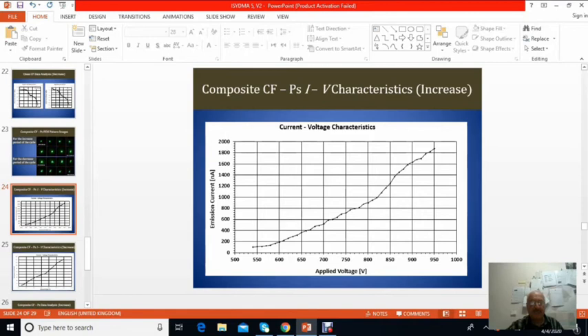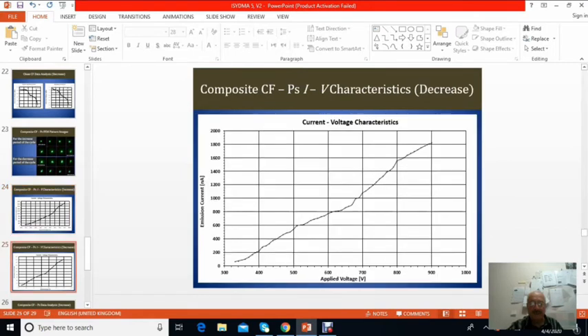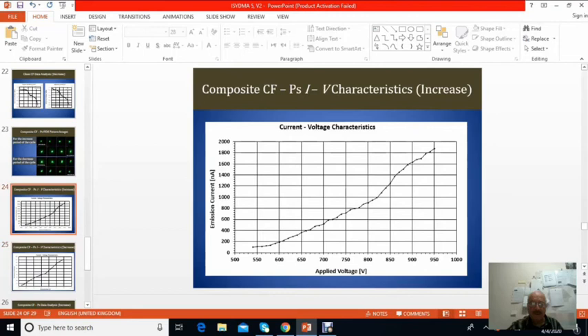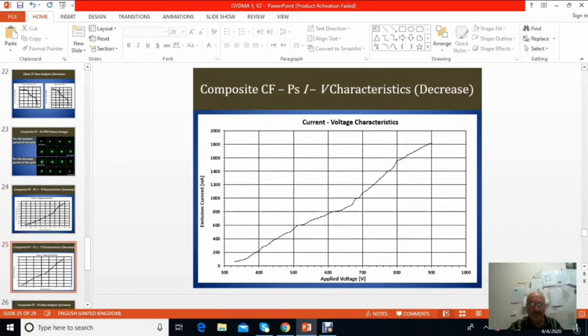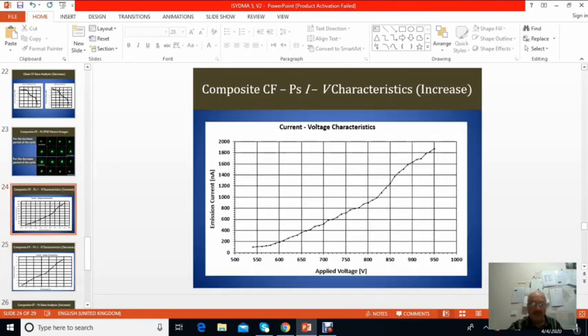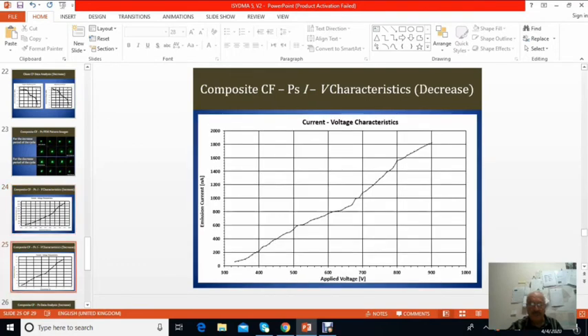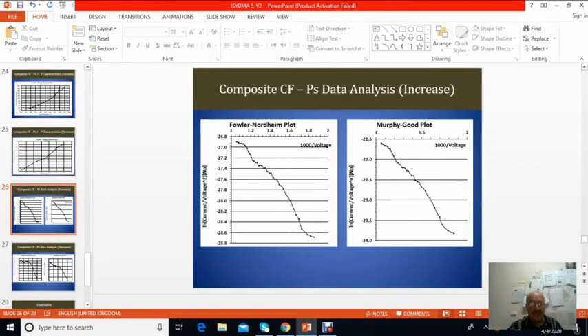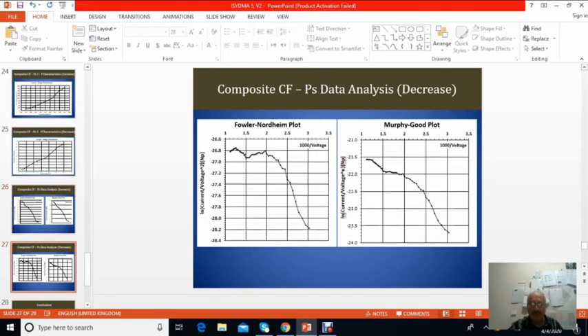This is the composite carbon fiber polystyrene IV characteristics, the increase, and this is the decrease, the composite tip decrease value. So this is here 950 volts for 1800 nanoamperes, 900 for 1800 nanoamperes. So not much difference in this case. And this is the composite carbon fiber, and this is the Murphy-Good plot here in the increase cycle.